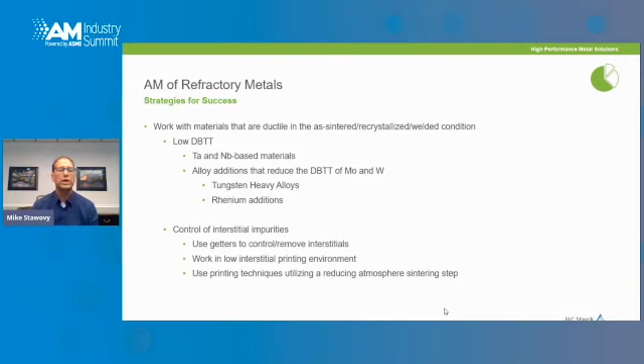fusion approaches. You can also use an alloying approach, and so some things that we've done with HC Starck, we've done alloy additions that help to reduce that ductile brittle transition temperature of molybdenum and tungsten, and a couple of things that we've demonstrated. You can add nickel and iron components to tungsten to make an alloy called tungsten heavy alloy, and that's a good fit for binder jet printing. And you can also do rhenium additions to the tungsten or molybdenum to make them more ductile at room temperature in a melted condition.